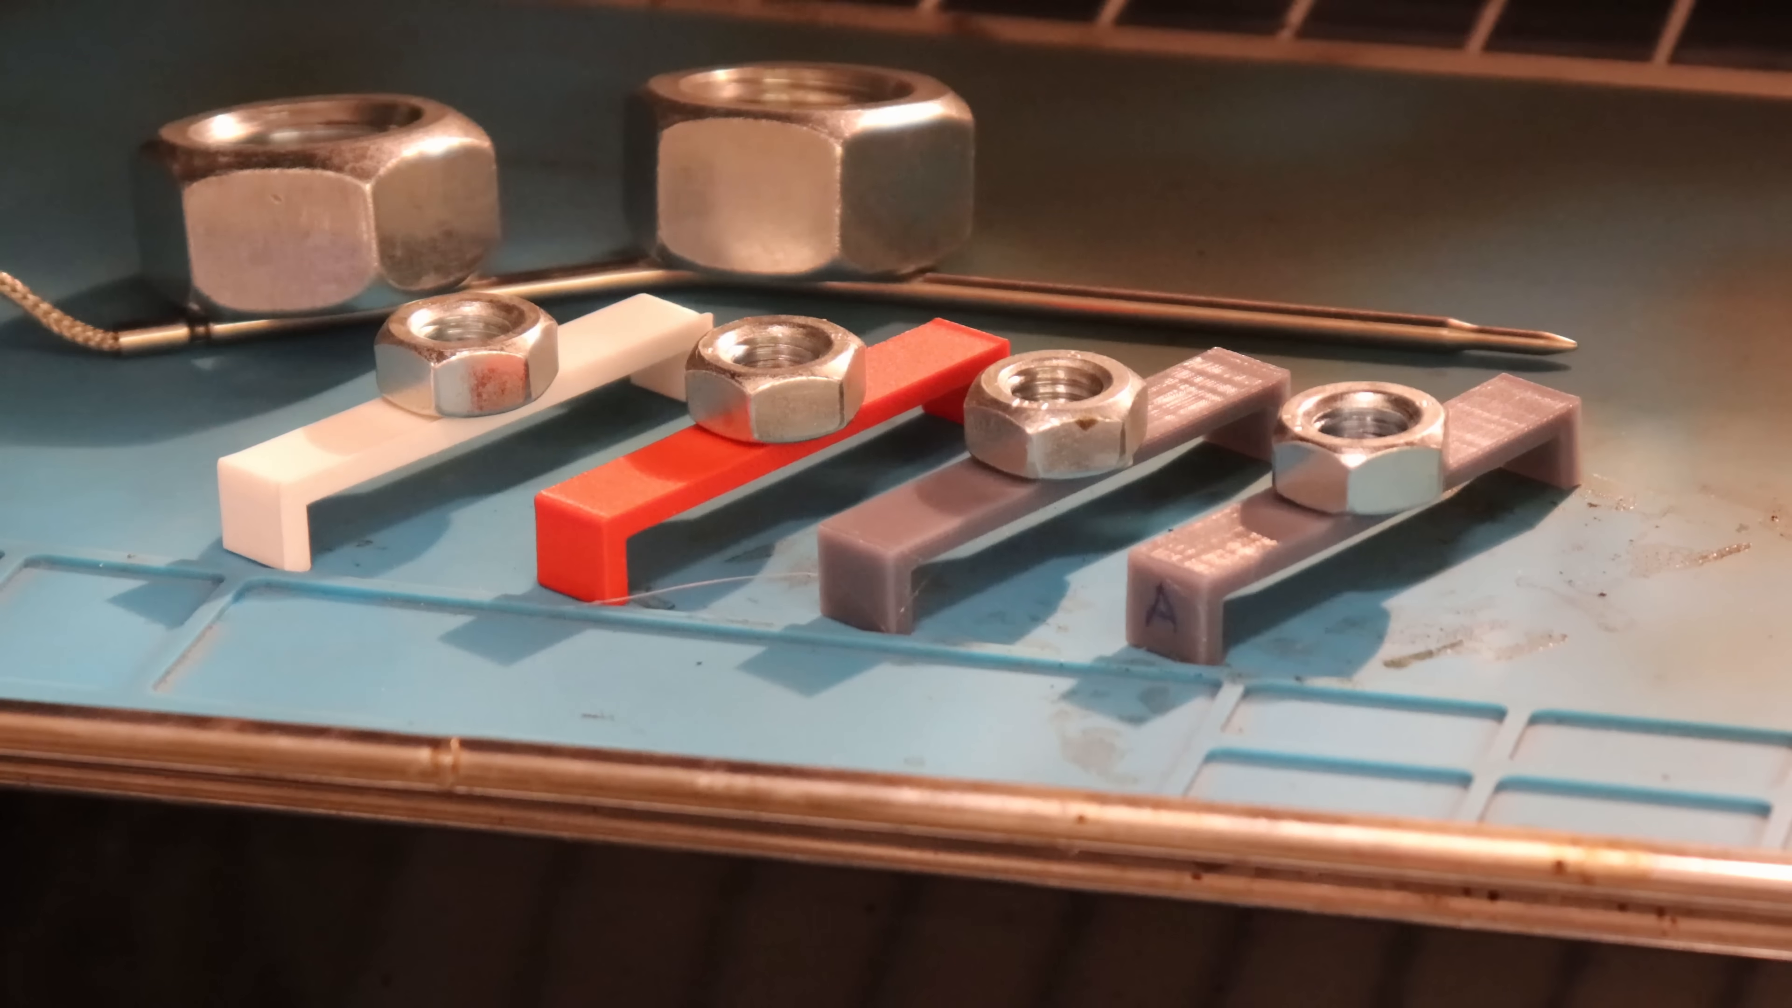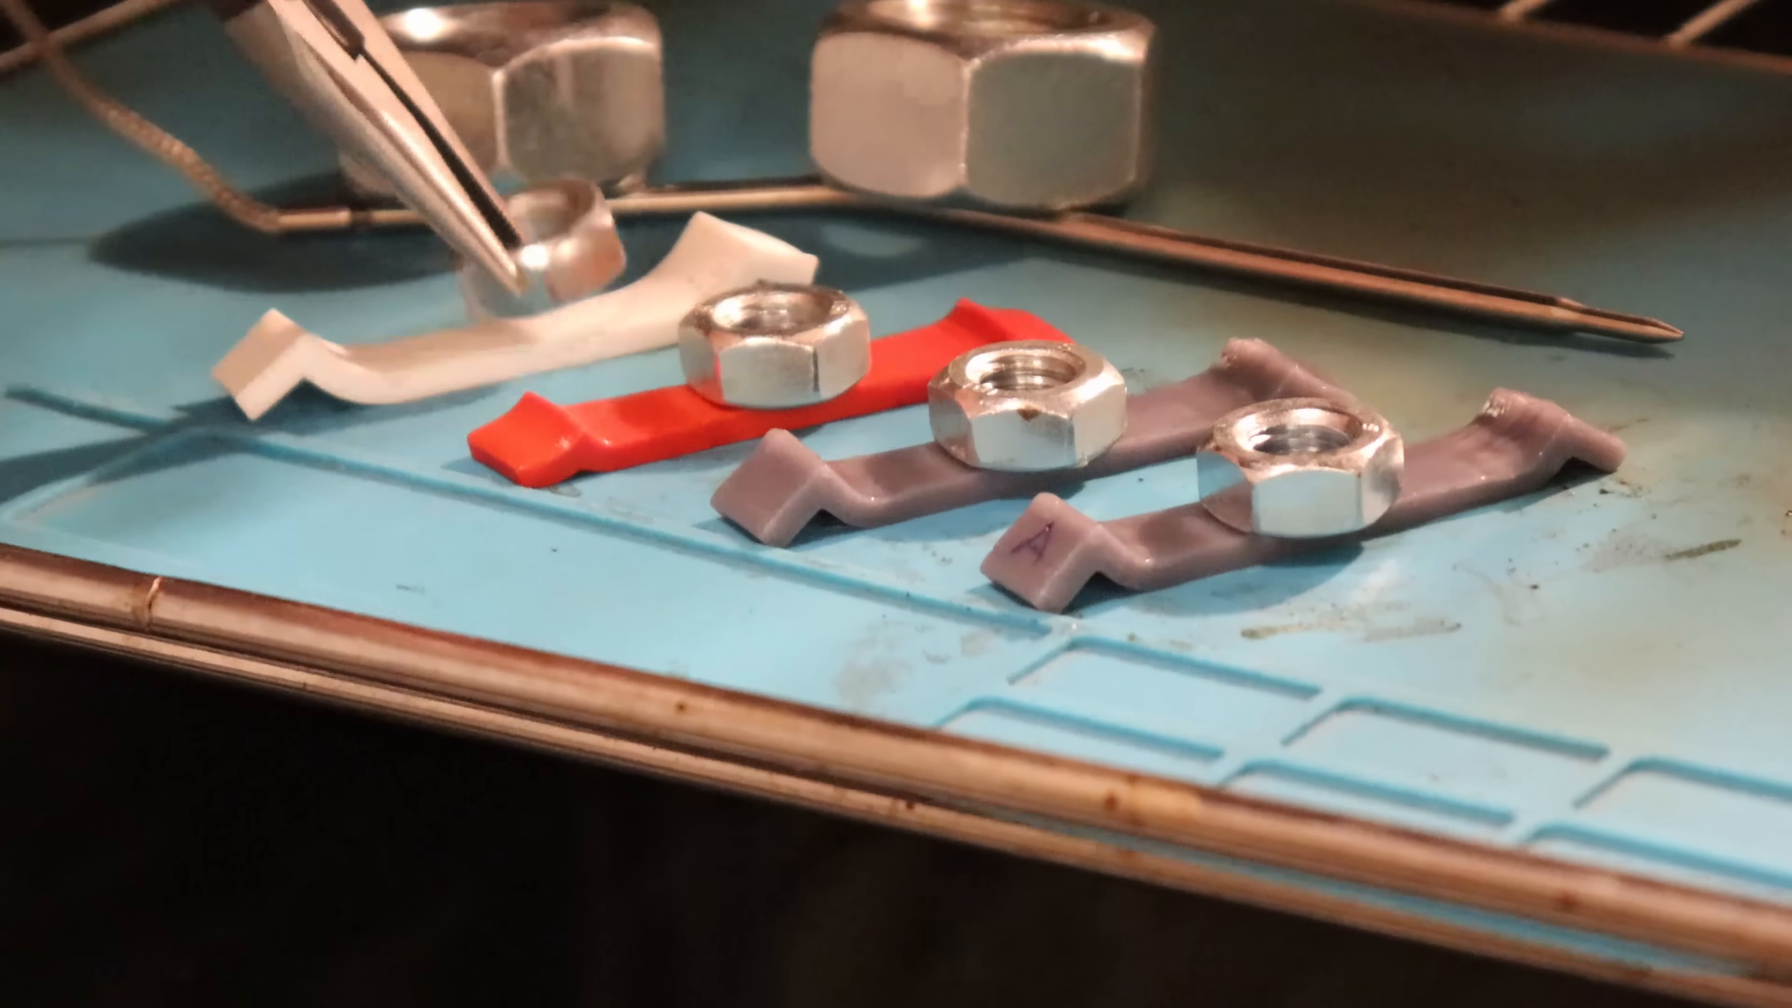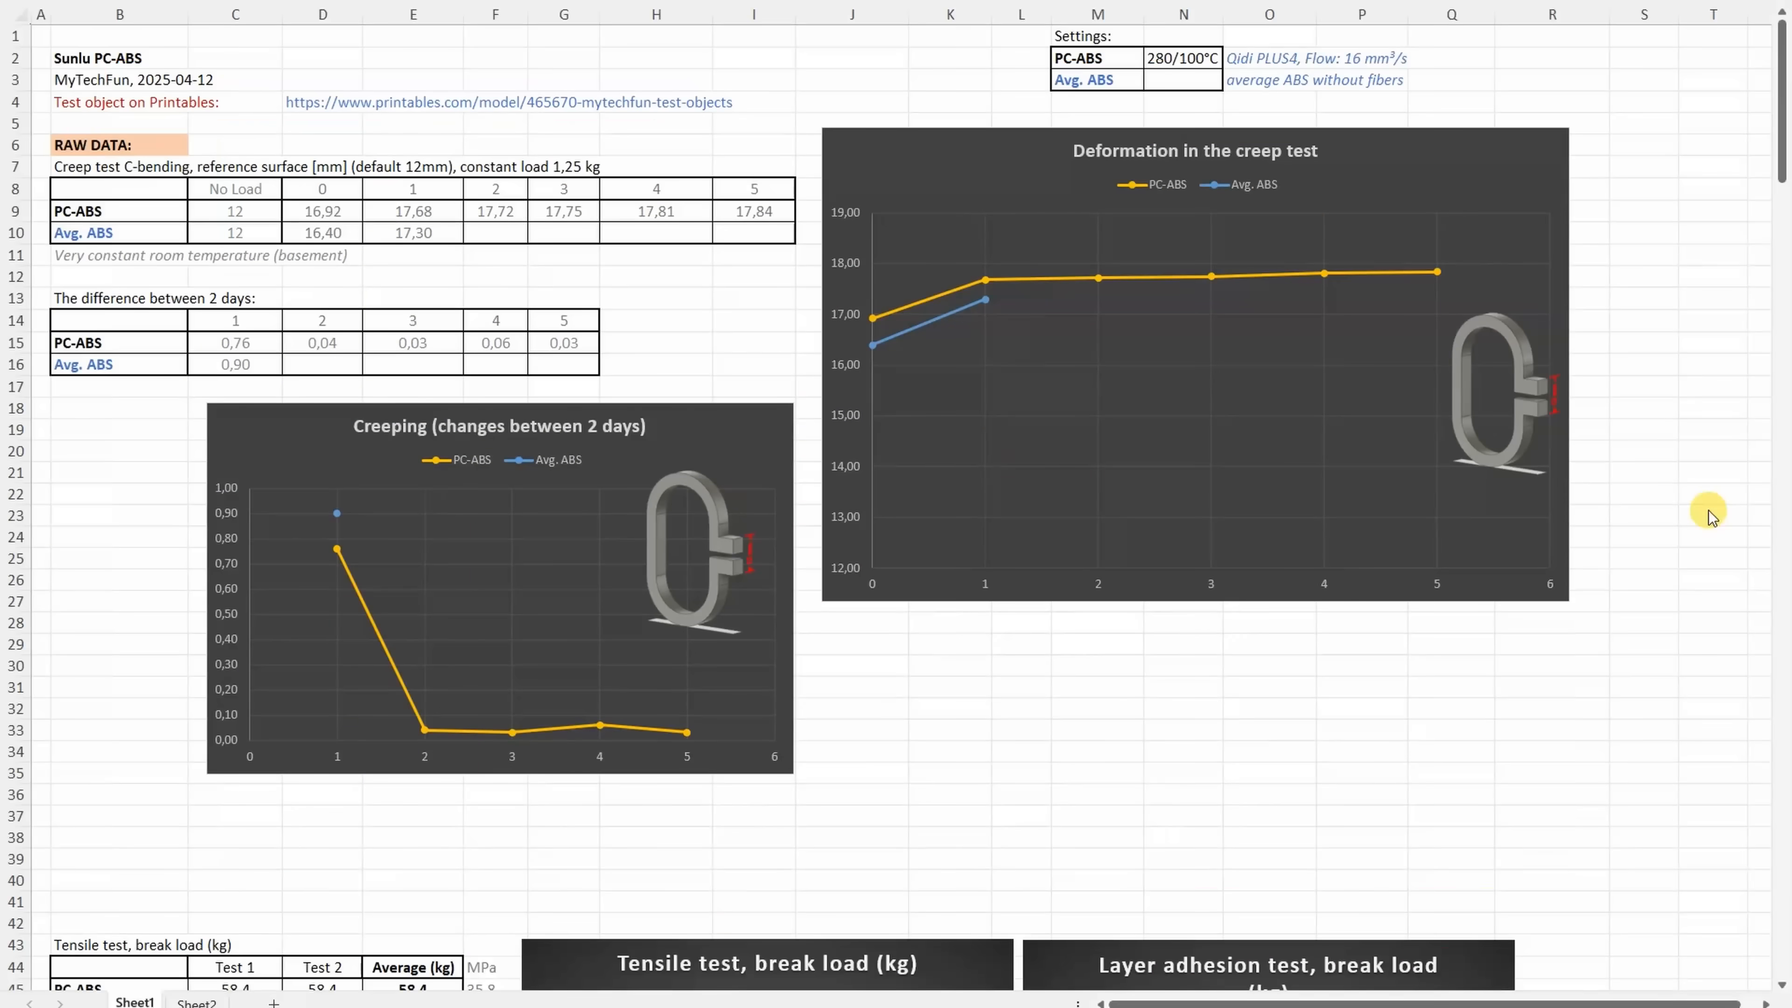Temperature test in the oven. I have several tests in progress. This is PC ABS, this is sped up timelapse video. This PC ABS started with deformation at approximately 120 degrees Celsius. The testing I stopped at 150 degrees Celsius, but this was too high temperature for all 4 objects. They became too soft and flexible. And one more time.